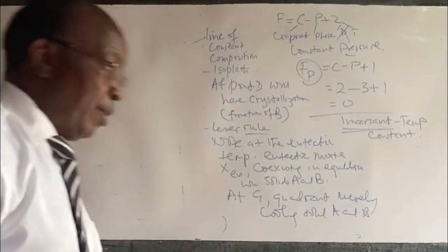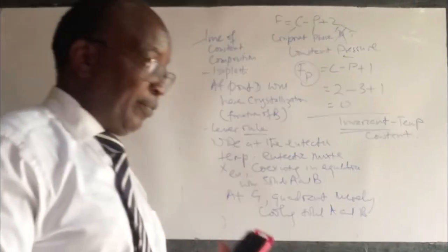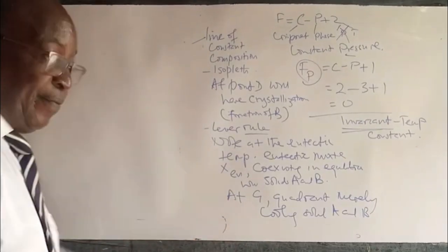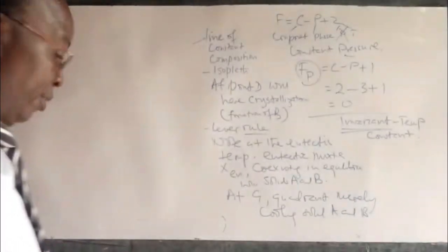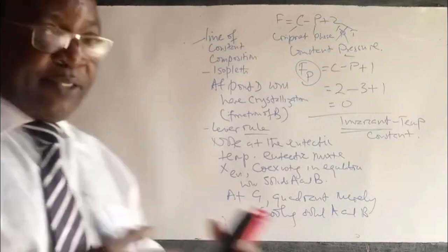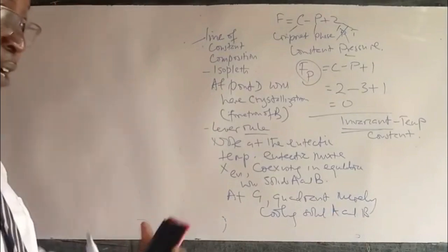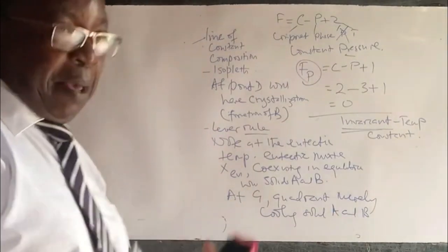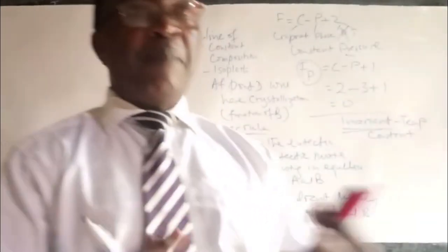And we have seen now that if you take any state point, other than the eutectic point, which we are going to see in thermal analysis, you will see that you will have crystallization, and as you continue on, the liquid phase disappears completely, and now you have only the two solids which are cooling. And remember, in the two-phase region, we can use the lever principle to tell the relative amounts of those particular components.